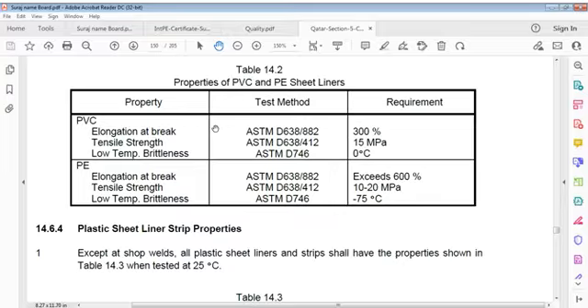Then PE, elongation at break, is exceeding 600%. PE is more elongated. It has elongation power. Tensile strength is 10 to 20 MPa. You can see it is about the same as PVC, but low temperature brittleness is minus 75. So you can say PE is better in that way. Then plastic sheet liner strip properties.